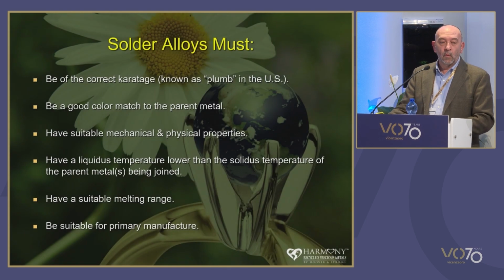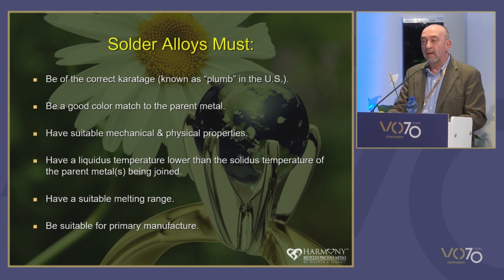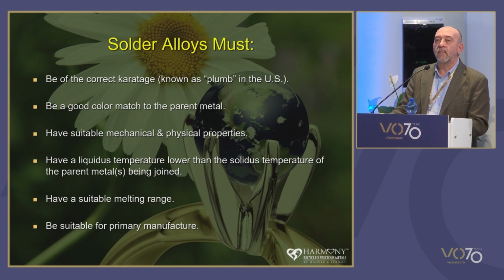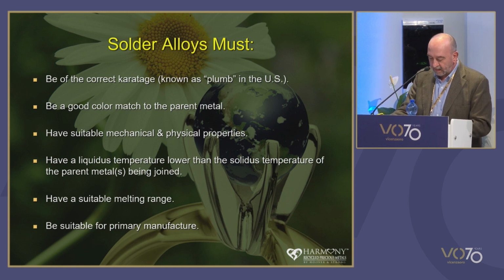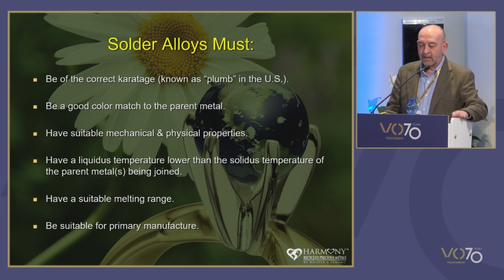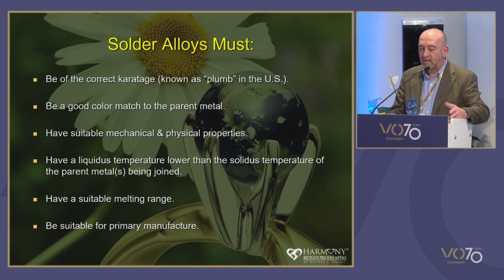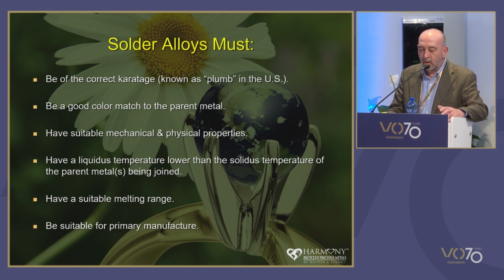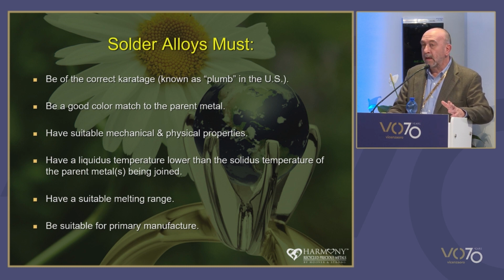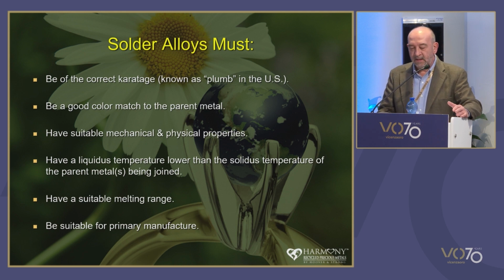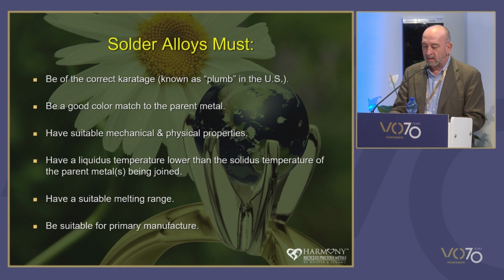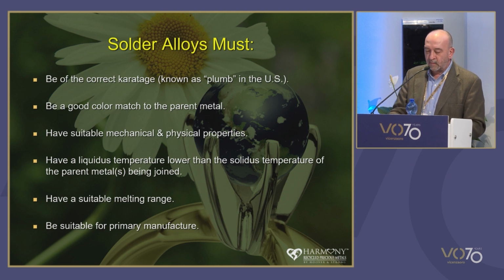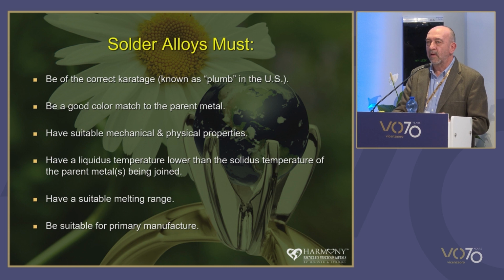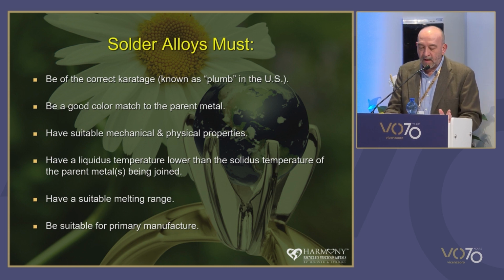So, the World Gold Council outlines the basic requirements for a solder alloy. First of all, it's got to be of the correct karatage, or as we call it, plumb in the US. It's got to be a good color match to the parent metal. It's got to have suitable mechanical and physical properties: strength, ductility, wear, tarnish resistance. It's got to have a liquidus lower than the solidus of the parent metal or metals. It's got to have a suitable melt range or melt gap. But most importantly, it's got to be able to be primary manufactured into sheet or wire by a solder manufacturer. There should be no problems with melting or casting, rolling, or scrap recycling. A solder can be great for joining, but if a supplier can't make it into a saleable product, then it's not a good solder.